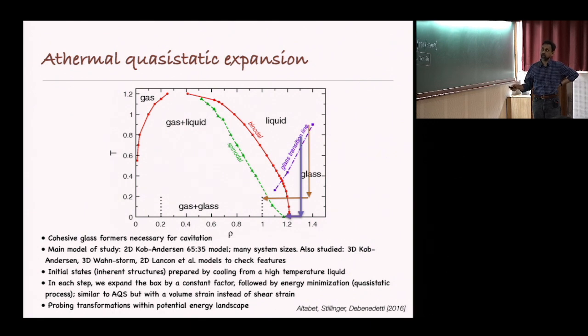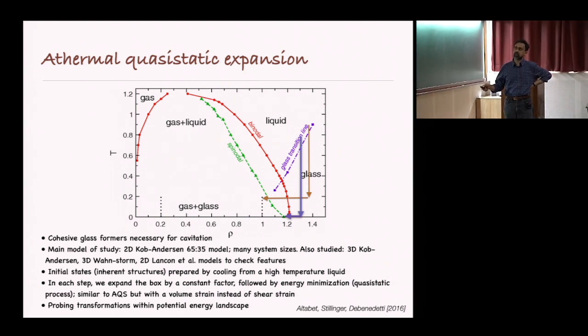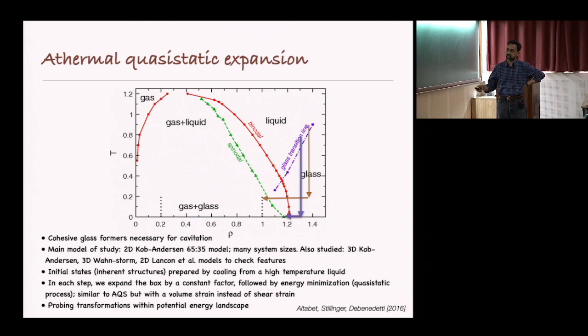What happens is that if you take a high density liquid, you quench it, you form a glass, and then you start expanding it. Eventually, this material will find its way into this gas plus glass coexistence region, and that will lead to the formation of cavities.